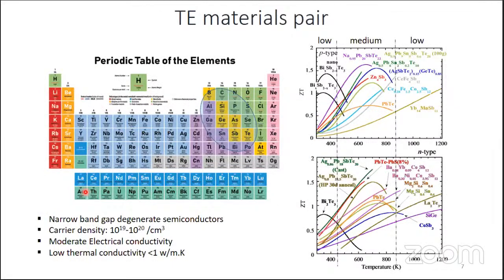Coming to the thermoelectric material, as this is very critical for making a power generating or Peltier module, we need a P and N type material, and mostly it's a narrow band gap degenerated material taken from this group. One of the elements should always be from this semi-metal group, this one.